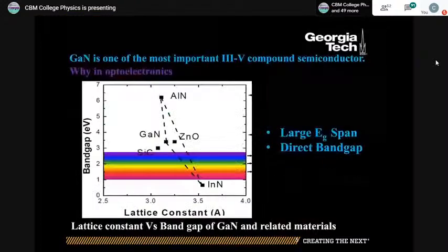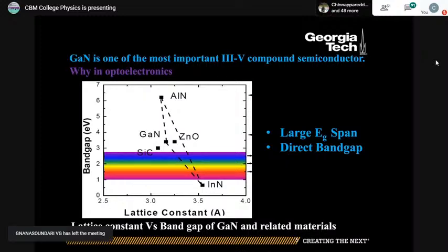So here is the band gap. You see all three nitrides except boron nitride, which I'm going to deal with a little bit later. So here you see gallium nitride, aluminum nitride, and indium nitride, all three nitrides, and related materials, zinc oxide and silicon carbide, are related materials to three nitrides because they all have wide band gap. If you see, indium nitride has a lower energy when compared to gallium nitride and aluminum nitride. So indium nitride can be alloyed with gallium nitride, and we can cover all the visible part of the spectrum here